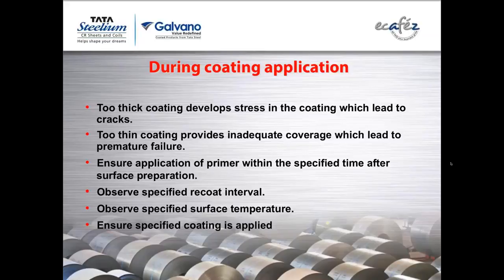Mr. Anand Bhagwat asks: we are using Aluzinc 2 mm and 1.5 mm sheet in our products, in the case of an IP23 compartment, and where this Aluzinc sheet is used at edges we find rust. What could be the coating process to avoid the rust in this case? Yes, on GI and Aluzinc, when we cut it, what is the cutting method is also important, because if you cut it with flames or lasers, sometimes the zinc will melt and come onto the edges, which will avoid the rust. But if you shear it, then this kind of problem comes. And with coating only, you have to do it.